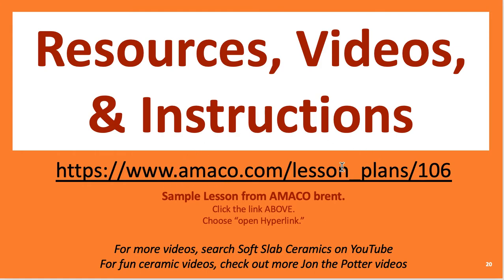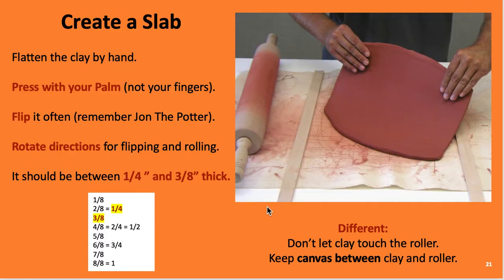Resources, videos, and instructions — this is where the lesson information came from; it's a little different from our exact lesson. Flatten the clay by hand: press with your palm, not your fingers. Flip it often and rotate directions for flipping and rolling. It should be between a quarter inch and three-eighths of an inch thick — a quarter inch is two-eighths, and three-eighths is a little bigger than that. Reminder: don't let the clay touch the roller.